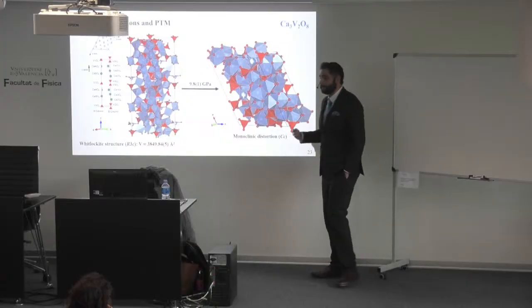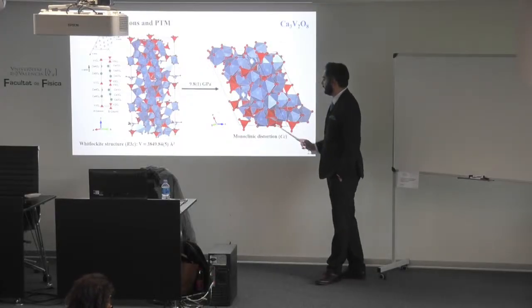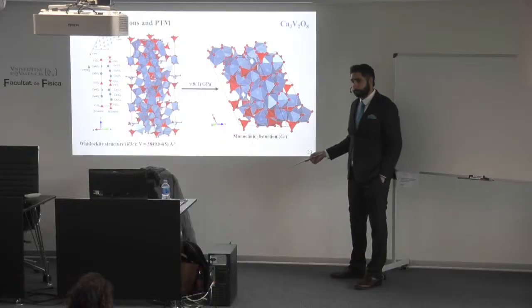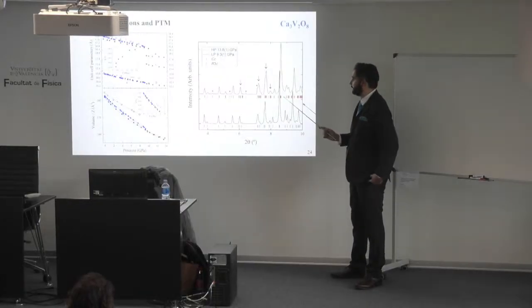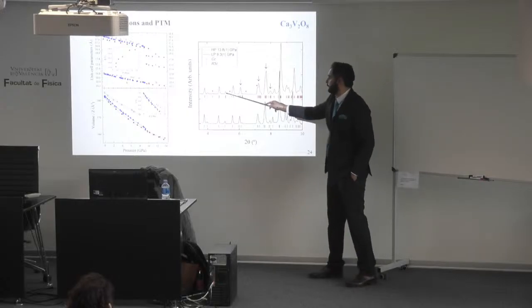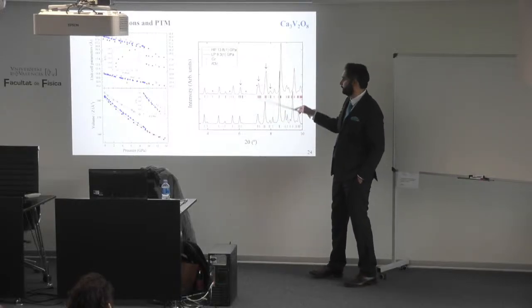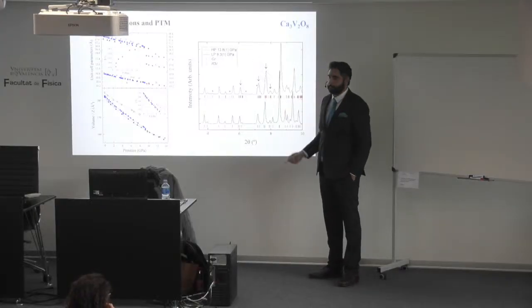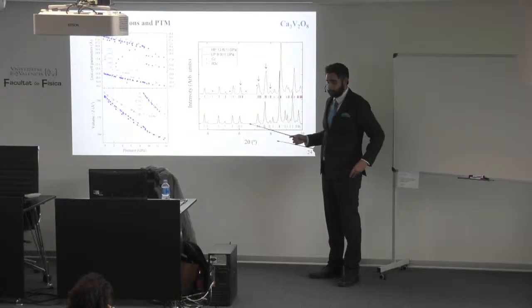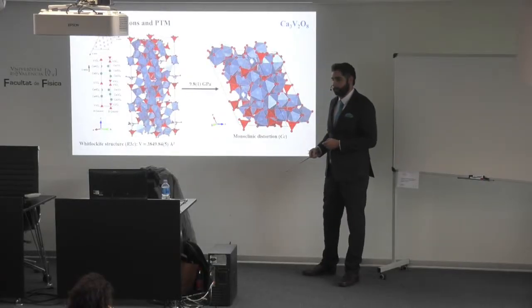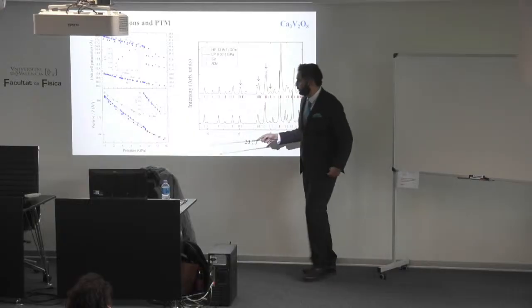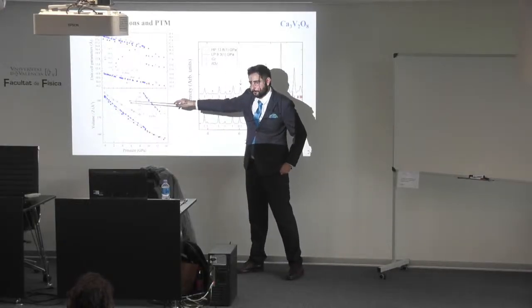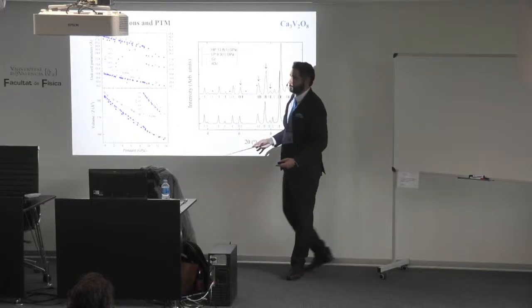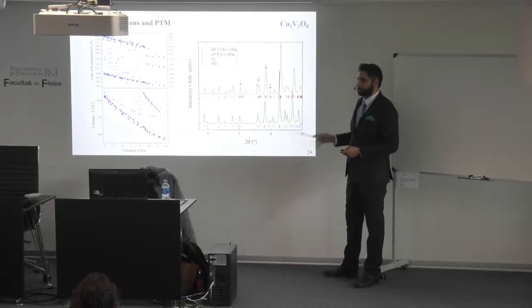In this case, we indeed had a phase transition at around 10 GPa to a monoclinic distortion of this group. Of course, it happens because we have some extra peaks from one pressure to a higher one, but we suspect it's because of the pressure transmitting medium. We are using methanol, so the pressure limit was around 10 GPa, exactly the transition pressure of this material, and the calculation said that it should stay in the same structure. So we suspect that this is driven by the pressure transmitting media.